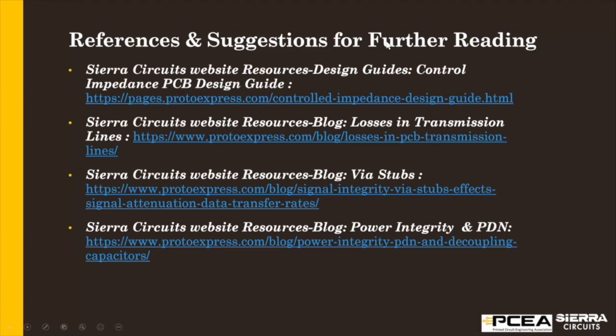Now, let's put it this way. As indicated over there, we have various conducting layers. You can have a plane and you can have a signal layer. Generally on signal layers, more of the copper is etched out, so the remaining copper percentage is roughly of the order of 20-25%. In the stack ups which we showed, the copper percentage on signal layers was shown as 24%. That's an average. Every manufacturer has different things, but from our best practices, we have found that 24% works. If we use 24% as the copper percentage at the design stage, then it is quite okay, and the manufacturing comes out pretty fine.